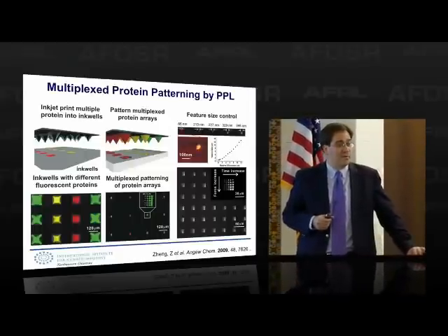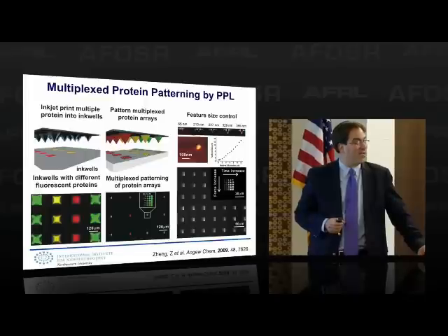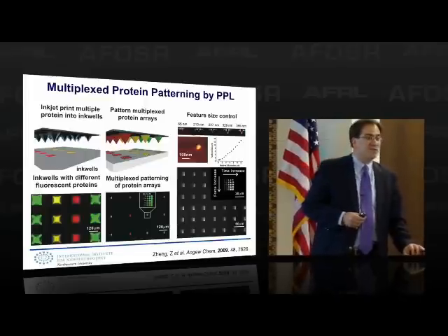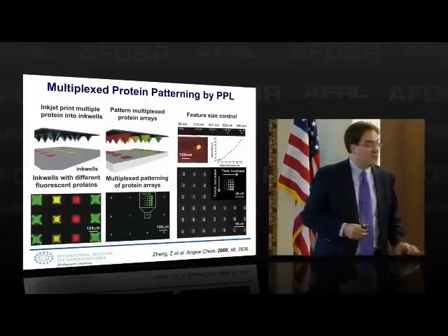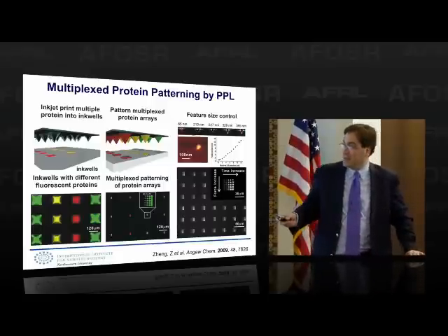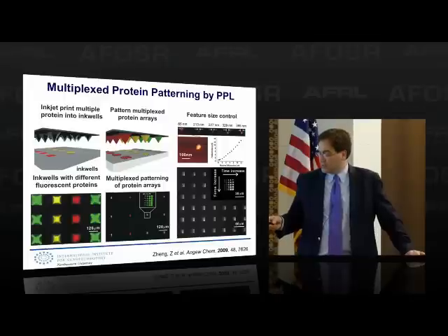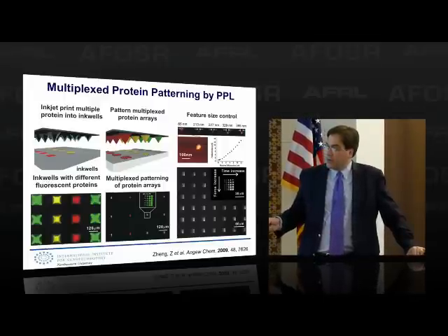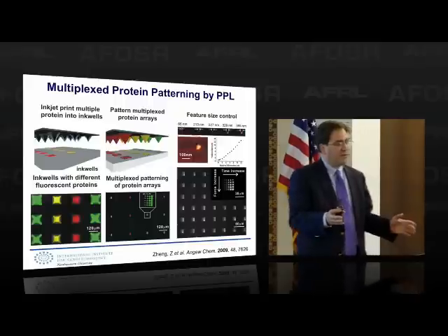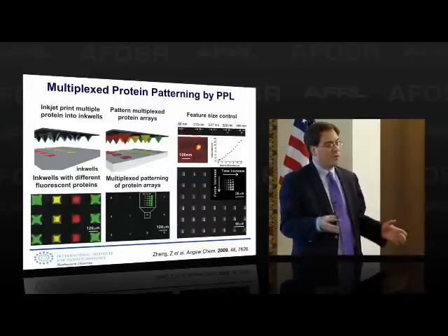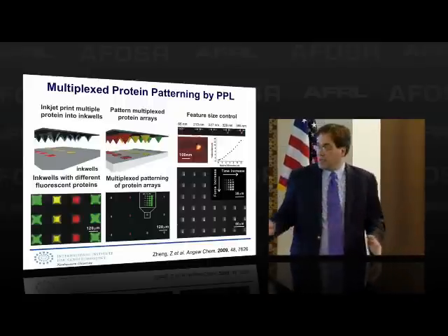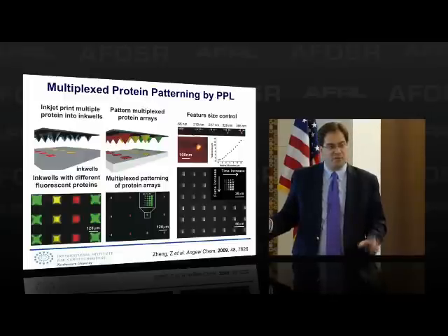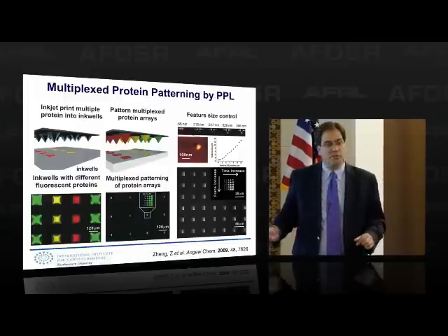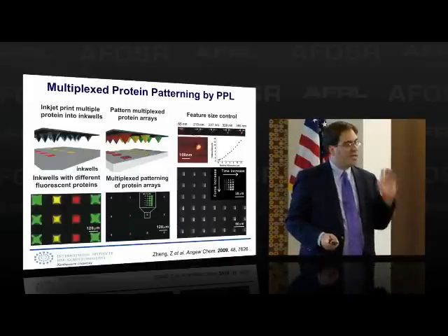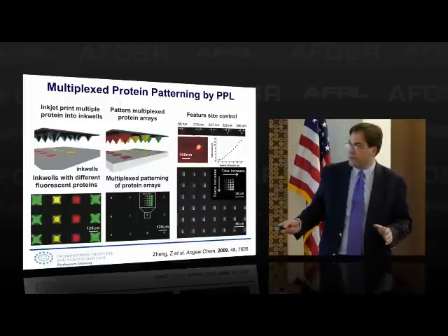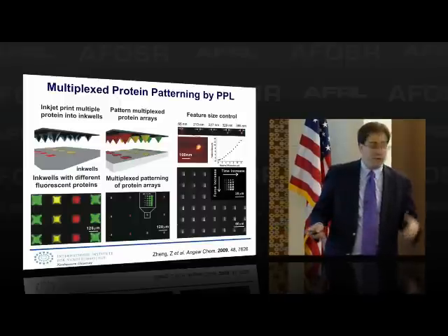Second thing you'd like to be able to do that a desktop printer does quite well is it uses lots of inks. In our case, inks are not defined by color, they're defined by composition, so we have a much bigger palette to choose from. And many of the structures that we'd like to work with are biological systems. So you can see here, we can take the mold that was used to make the arrays. The tips are nanoscopic in terms of sharpness, about a 60 nanometer radius of curvature. The wells, though, are microscopic in size, and you can hit them with an inkjet printer. So you can fill the wells with anything you'd like that you can transport in a printer.